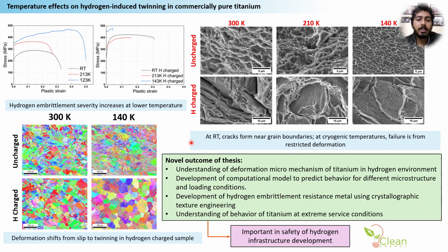To further understand the service condition and hydrogen susceptibility, we did cryogenic tensile testing, in which the commercially pure titanium generally shows very good strength and also ductility. However, in the presence of hydrogen, there is a drastic reduction in the ductility, and this is due to the deformation shift from the combination of twin plus slip deformation to only twin deformation that is happening at cryogenic temperature.